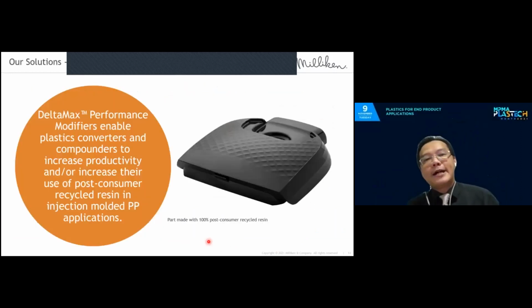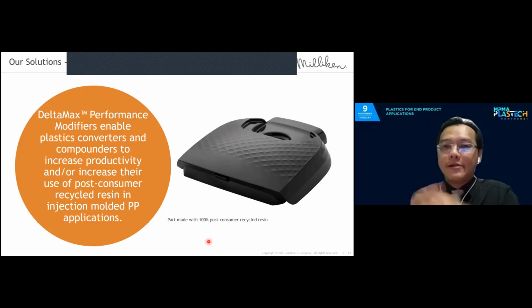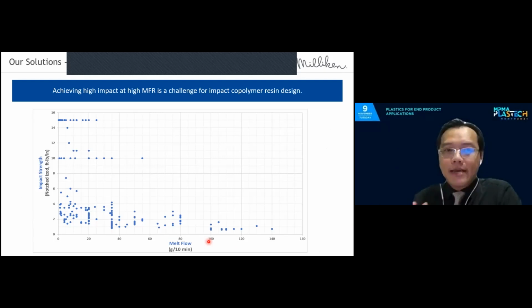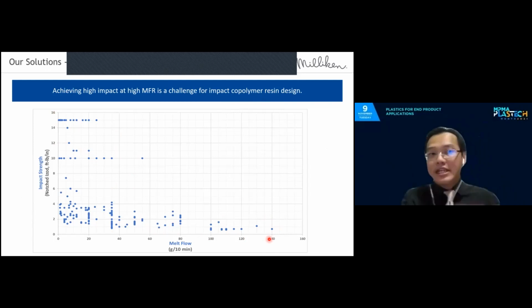Moving on. So Deltamax is a very new-to-the-world technology, part of which also helps in optimizing the processing conditions of an injection molding process. But to take a step back, we are focusing here on impact copolymer polypropylene or block polymer polypropylene, right? For injection molding, the higher the MFR, the easier your injection molding, with a wider window, especially if your parts are large or your flow paths are very long.